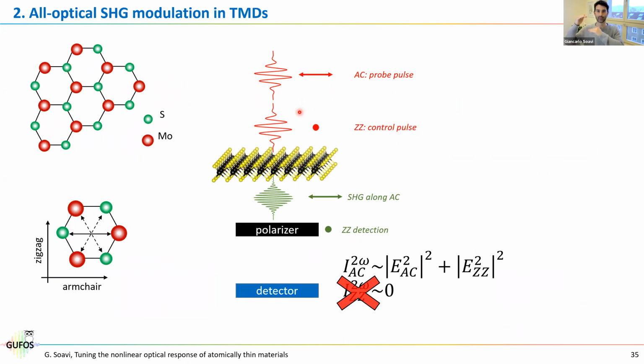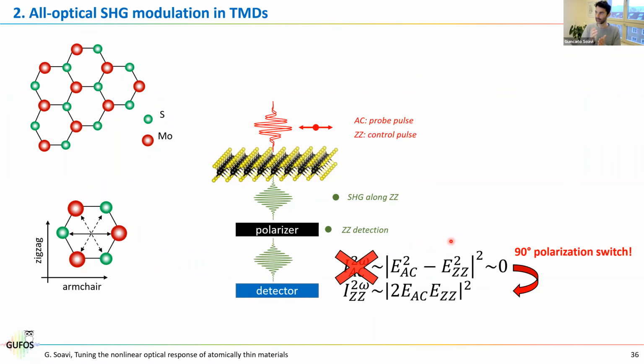And then we do the following experiment. We separate our pulses into 2 and we now polarize one of them along the armchair and one of them along the zigzag direction. Now, when the two pulses are far away from each other, both of them will contribute with a signal along the armchair direction because I take the sum of the two and they do not interfere. However, when the delay between the two pulses goes to 0, then I have to look at the difference between the two, and this difference will go to 0, and the product will be maximum. So everything will be emitted along the zigzag. So basically, I have this 90 degrees polarization switch. Now I simply place a polarizer in front of the detector, and by doing that, I can switch on and off the second harmonic generation by a factor of 100.